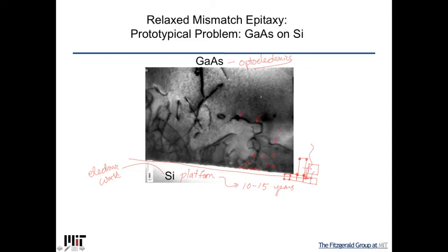They cannot end in a crystal, and so what happens is you end up with all these defects threading up through there, and they make the gallium arsenide not very good for any application. And so the terminology is those are referred to as threading dislocations because they thread up through the deposited layer. Even though actually they're the same dislocation, for example, this thread,